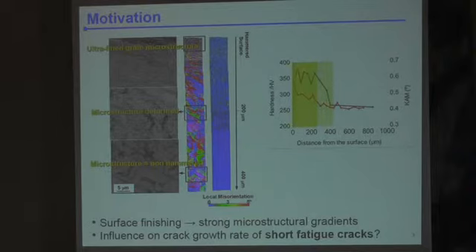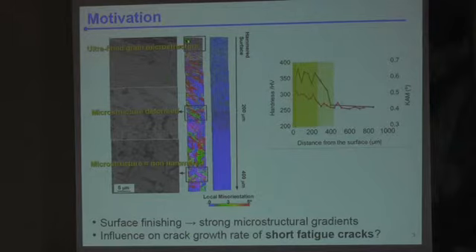This is a slightly different process, but I think it gives a good idea. This is hammering, which is tapping on a weld to improve the fatigue properties. So you see an optical micrograph of the structure. It's ferrito-pearlitic steel, and it's close to, but not in the heat-affected zone. You can see that the size and the shape of the grain is changing. This is the corresponding EBSD map with some very small grains at the surface, and this is the kernel measurement telling you that you indeed stored a lot of plastic deformation, dislocations, close to the surface.